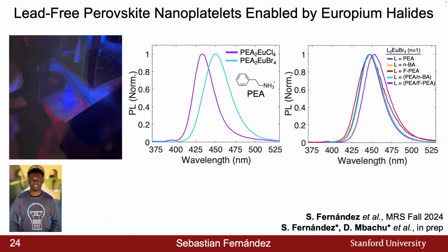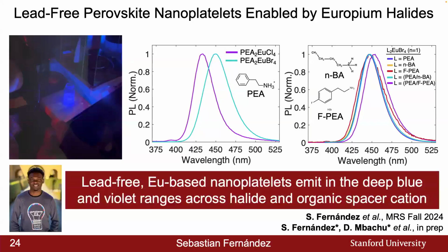We can also look at forming these nanoplatelets across various ligand species. Here we have n-butylammonium and fluorinated phenethylammonium, and also mixing them with one another. In this case, we see not too much tunability, which makes sense because we have, in theory, the same kind of thickness within the nanoplatelets themselves, really showing that this is a new material that can emit in the deep blue and violet ranges across organic spacer cation.